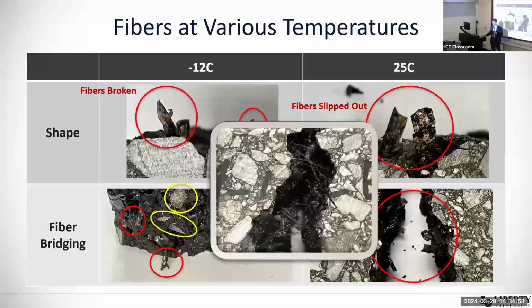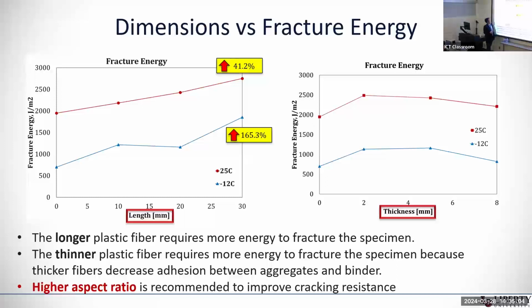Okay, so this shows the nylon fibers. It looks very hairy, so we have a lot of fibers on it. Here is dimension versus fracture energy. As you see, we increased the length by keeping the width of the fiber at 5 millimeters, and increased the length of the fiber from 10 to 20 and 30, and then put it into the mixture. It shows that as we increase the length of the fiber, it increases the fracture energy, which means the longer fiber can resist crack propagation better than the short fibers.